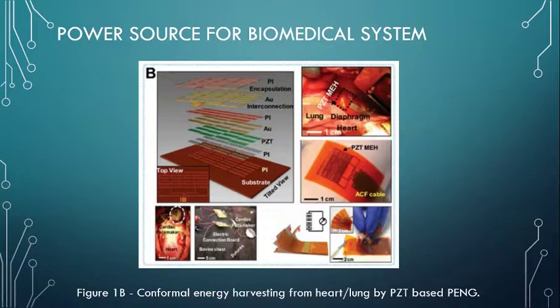In this work, simultaneous energy harvesting and storage were achieved by full integration of the PENG, rectifiers, and microbatteries. The research indicates strong feasibility of achieving self-powered, implantable mechanical devices. This work also provides an interesting demonstration of 5 independent PZT harvesters connected serially in a multi-layered stacked flexible PENG. This multi-layered flexible PENG could generate 8.1 volts of voltage and 1.2 microwatts per centimeter squared of power density, which were much higher than the output of the single-layer device.